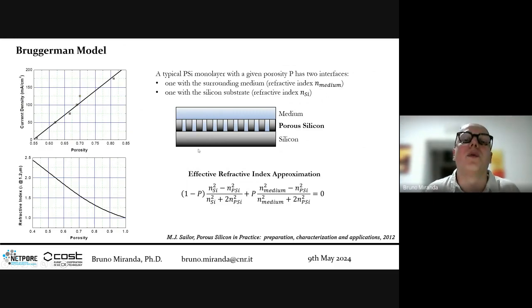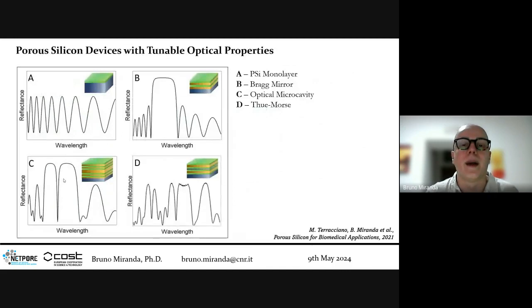So how can you model the refractive index? You can use the Bruggerman model, an approximation in which you have the refractive index of silicon and the refractive index of the medium, both well known. Knowing the porosity, which you can derive from this curve, you can extract the average approximate refractive index of the membrane.